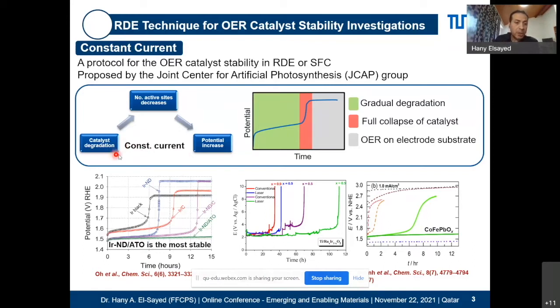When you apply a constant current, and catalyst degradation is taking place, we will lose some of the active sites. So the number of active sites of the catalyst will decrease. For that reason, the potential will have to increase in order to keep providing the constant current that we are asking the cell to provide. As a result, you will see an increase in the potential with time, and all of a sudden you get this sudden increase, indicating that the catalyst is not only slowly degrading, but now all of the catalyst is gone. A lot of people are using this in literature, and this indicates a complete degradation of the catalyst. Here are some examples from literature, from 2016 and 2017 as well, and so on. All of them use this technique.